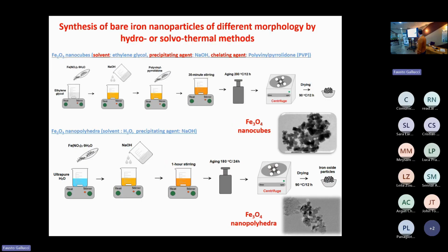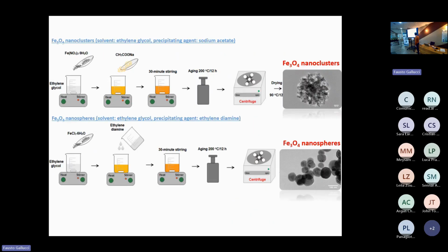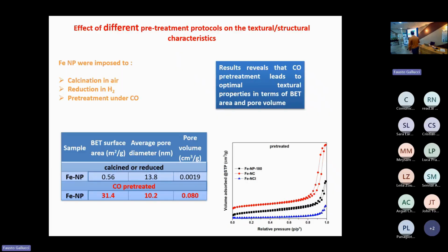Again, by following hydro or solvothermal methods and adjusting the solvent, the precipitating agent, and the chelating agent, we can obtain different nanostructures: nanocubes, nanopolyhedra, let's say, clusters, and nanospheres. At first, we explore the effect of different pretreatment protocols on the iron nanoparticles, imposing calcination in air, reduction in hydrogen, or pretreatment under carbon monoxide.